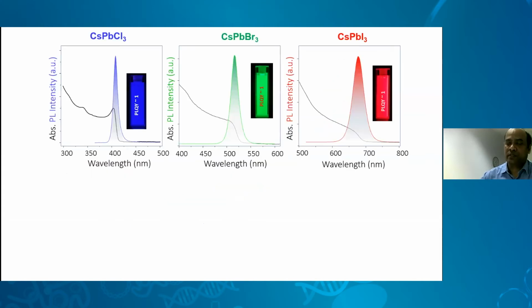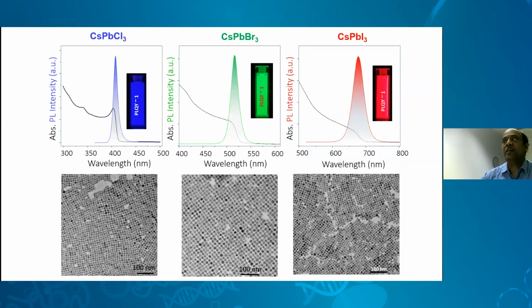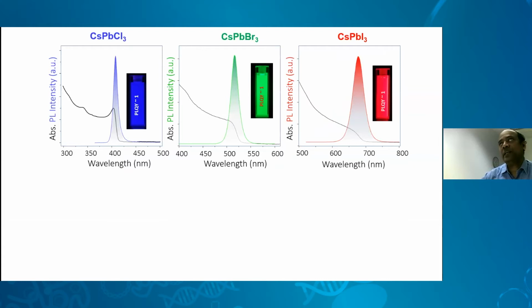So that's what happens in one reaction: changing the temperature, you can tune the size as well as the shape of these nanostructures. So now, what happens with the chlorides and bromides and iodides, though mostly I'm talking about bromide today, and 3 colors are well documented. These are all reported, with quantum efficiency that can reach near unity, around 80-90%, in different colors. And once you want to get an intermediate of blue and green, they can have mixed halides, so that the color can be continuously tunable in the entire visible region.